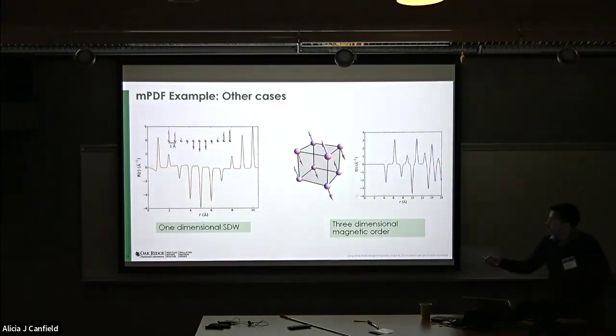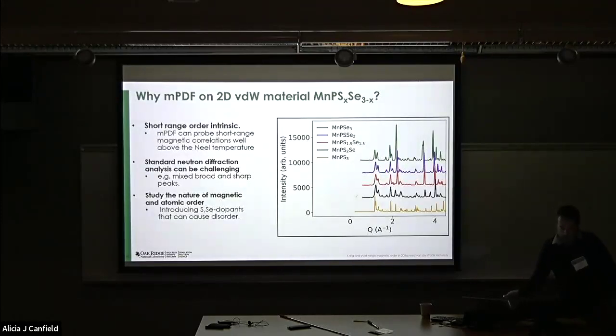So just a few more examples. You can see a spin density wave, and of course you can look at three-dimensional ordering as well. So why MPDF for this series? Well, short range order is intrinsic in these two-dimensional van der Waals materials. So this is a route to start to analyze it. Standard neutron diffraction can be challenging, as I've shown. And if you start to dope in, start to create some disorder, this is also a way to look at that, to see what the disorder is doing at the local level.